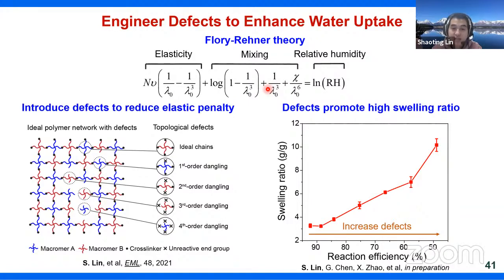Also, for many composite designs, hydrogel needs to be strong. It doesn't need to be soft. These are some applications I can think of. Also for some load-bearing tissues, for example, many people think we can potentially develop tissue replacements. If we think about the mechanical properties of tissues, they typically experience this J-shaped curve. The stretchability is not that large. The modulus is typically about 100 megapascal. So in those scenarios, that requires high toughness, high strength, but not that high stretchability. So basically, through your polymer network design, you can control a large variability of stiffness and toughness. Yes, different parameters for different applications. Yeah, that's good.